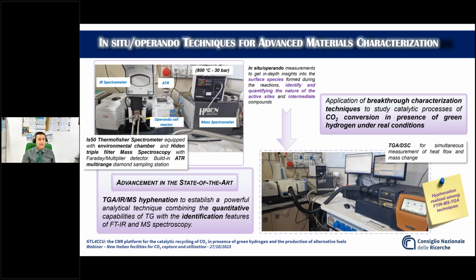Concerning the pillar 3, here we have an in situ operando infrared installation for advanced materials characterization. The main installation includes a latest generation infrared spectrometer equipped with an environmental chamber able to work under high temperature, I mean up to 800 Celsius degree and up to 30 bar, to monitor the evolution of surface species and intermediates under real conditions. So we can follow, monitor the evolution of a specific process over time.